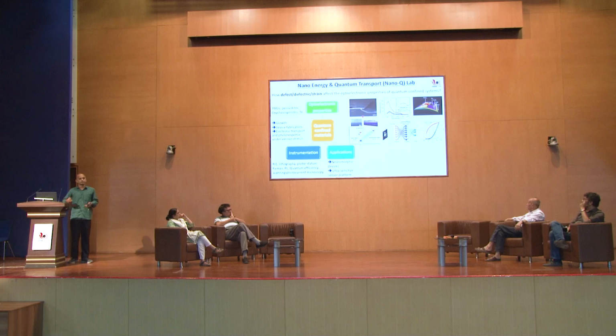So all these TMDs, they come with vacancies. Generally, if it is sulfur based, then the sulfur vacancies. If it is selenium or tellurium based, then the selenium or tellurium vacancies. Most of the time it is single vacancies, but what we found is that if you can introduce double sulfur vacancy, meaning two sulfur vacancies together, then those samples give very high mobility, which is really large compared to what you generally see in these materials. Okay.